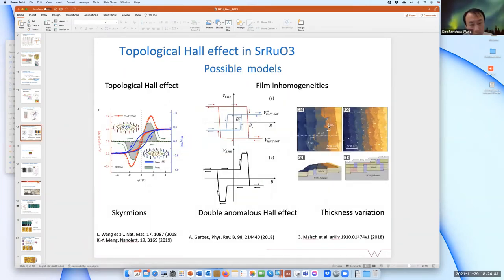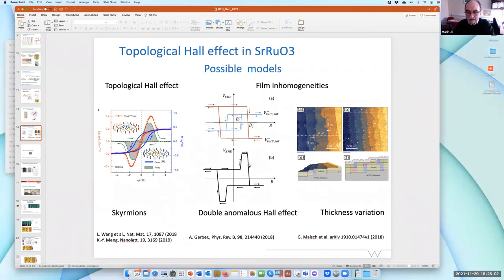You have different thicknesses due to the growth process with different patches, and each thickness has its own anomalous Hall effect. And then if you overlap those two effects, you get this one. This is a kind of mechanical vision of the topological Hall effect, and I don't believe it. Because we have to think about the electrons flowing in this direction or this direction, and if I have patches which are highly resistive, they will avoid them, or shunt the high resistance region. So you won't see those patches.